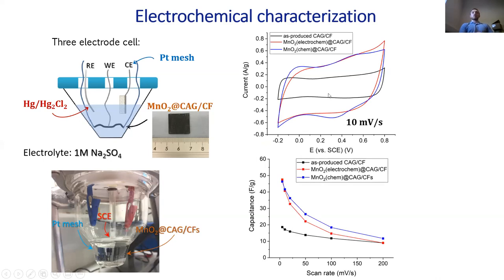These materials were characterized electrochemically in the three-electrode cell, which was introduced by Servann, although it has slightly different architecture. So again, the working electrode is our carbon aerogel modified carbon fibers in the typical aqueous electrolyte with the sodium sulfate salt. The cyclic voltammetries, which show us the capacity performance of our electrodes, illustrate that both manganese oxide samples actually exhibit similar shape and behavior, indicating that the change of procedure does not change significantly the performance of our